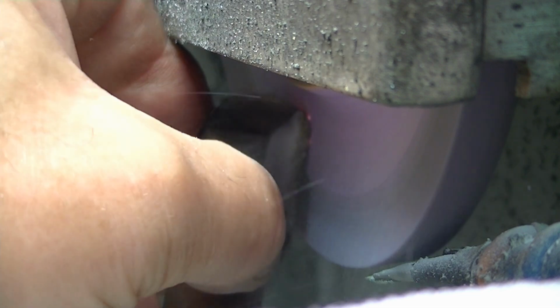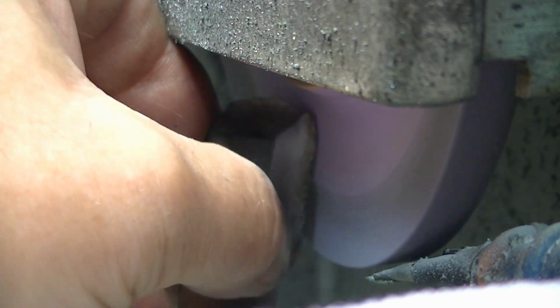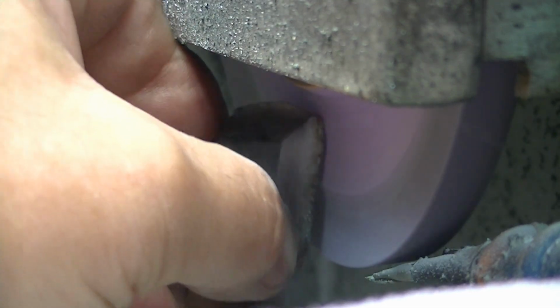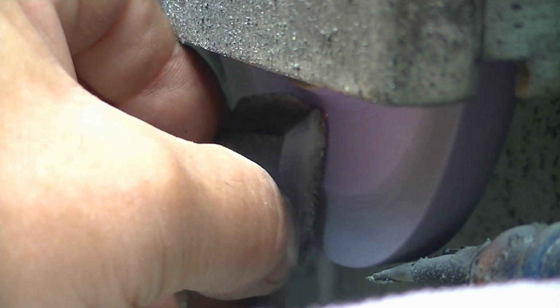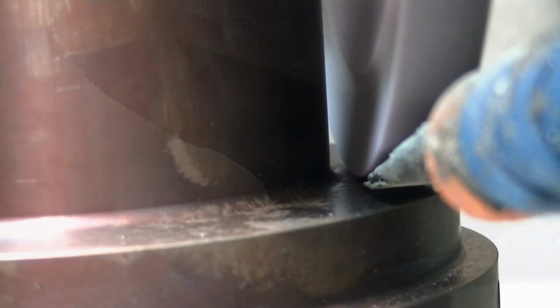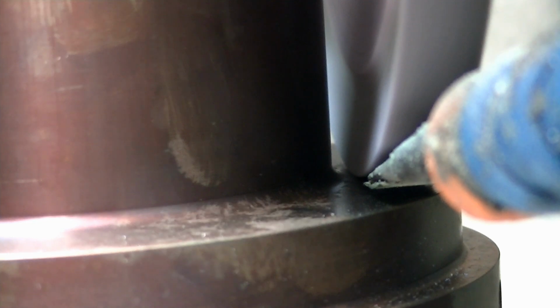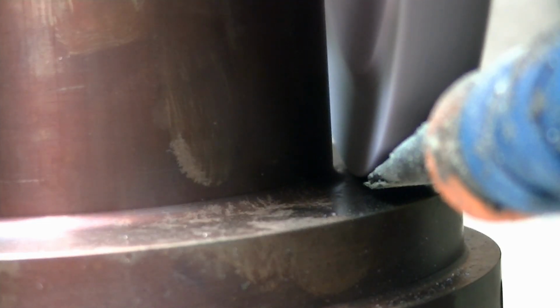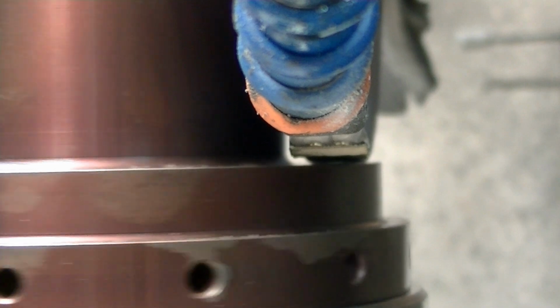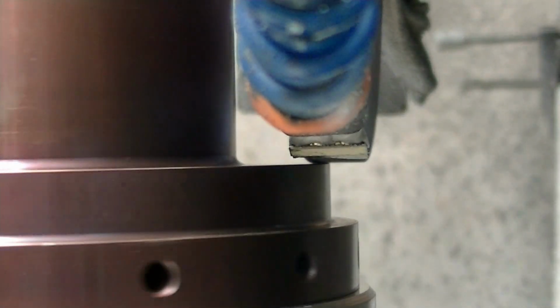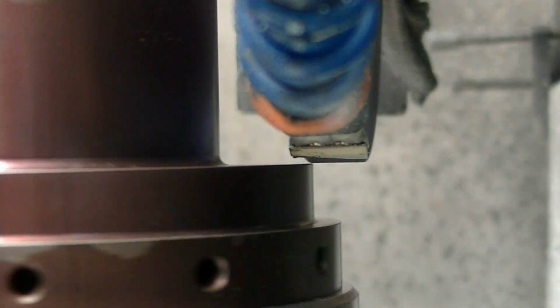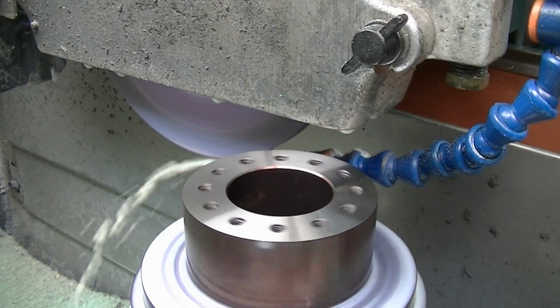Here I'm relieving the side of the wheel because I'm going to be getting down close to the shoulder, full length shoulder, and I need to clear this out so it doesn't run into the part. Here I'm touching off my Z position on the control for where it's going to stop and start its grind position. Here it's down feeding and traversing off the part. That's the automatic cycle.